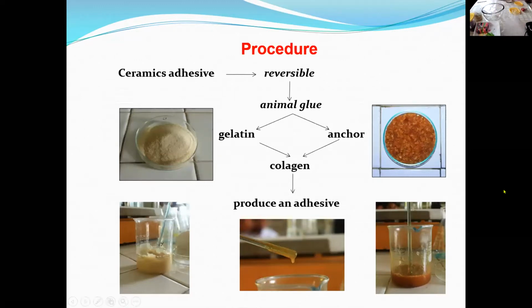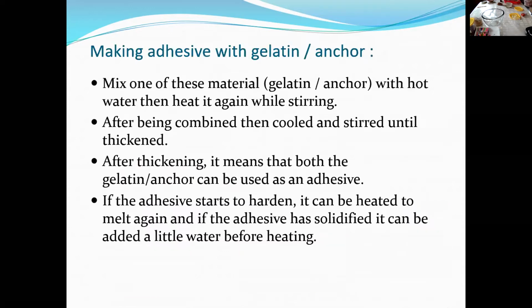This is the procedures that we do. From this material, from anchor or gelatin, we dilute them in water. One gelatin by 2 water. For instance, if we use 20 grams of anchor, we used 40 milliliter of water. It's easy to make.